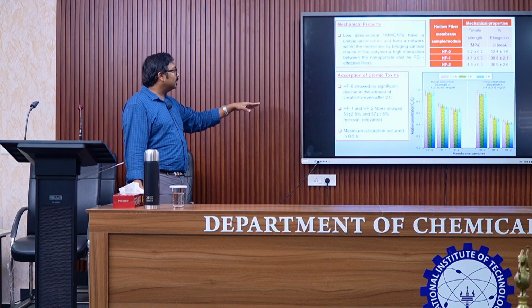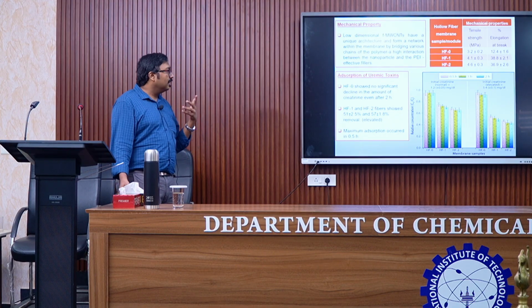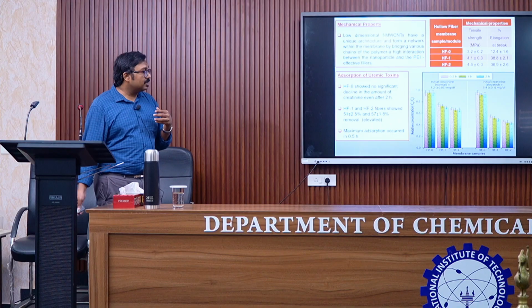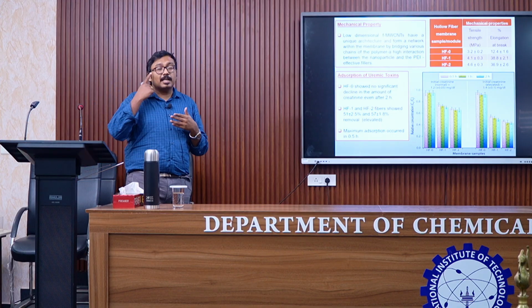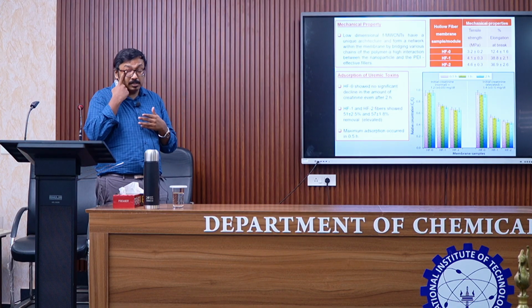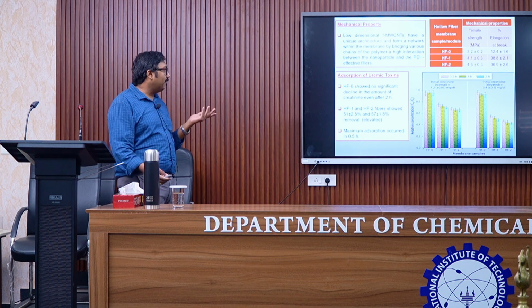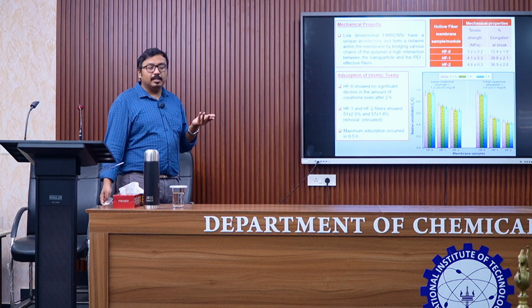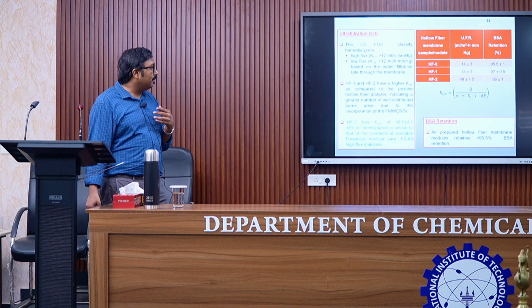So the relative concentration drops, meaning some part of the creatinine was adsorbed on the membrane surface. And the maximum adsorption occurred within half an hour, which is again good, because the entire hemodialysis run is around 3 to 4 hours for a normal patient. So if it adsorbs within half an hour, that is again a positive sign for the membrane.